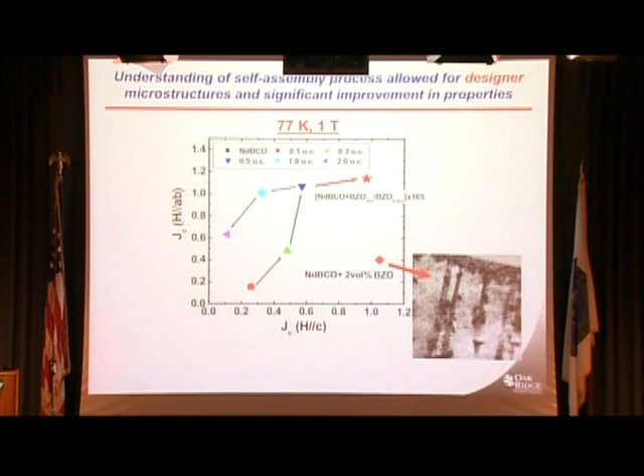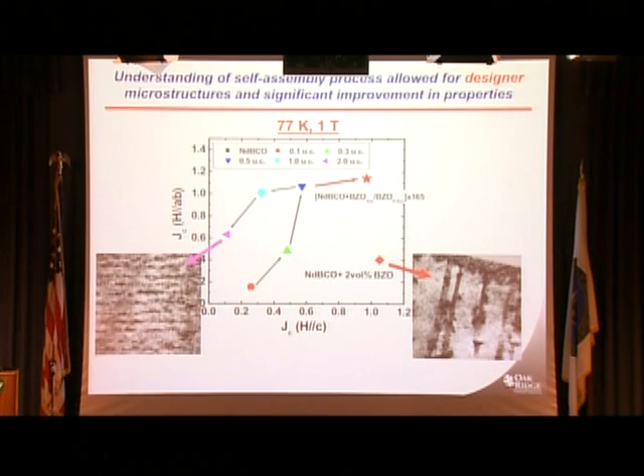So in the next view graph, we start out with the microstructure that I showed you previously with these nanocolumns and these 3-micron films. This is a plot of the amount of current you can carry when the field is applied parallel to these columns versus in the perpendicular direction. You can see in the perpendicular direction you have less ability to pass current than you have in this direction. So we really wanted to get from here to here so that we have the same amount of capability in both directions. Well, we can do that.